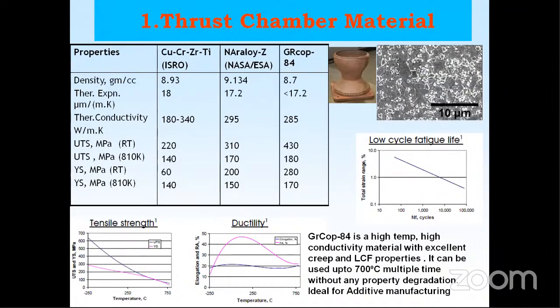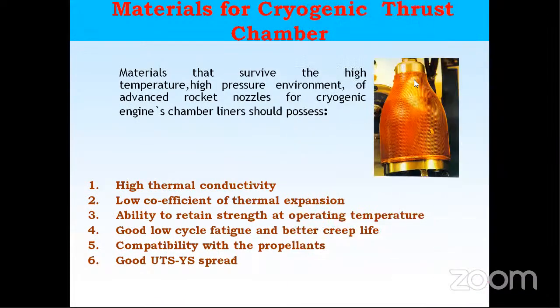Because what happens, my material, we make a chamber. This is a chamber actually. So we do brazing. We braze the foil and close the channels. The brazing temperature is nearly 1030 degrees centigrade, and after that it goes for engine operation. Actual engine operation is about 600 degrees centigrade. At that 600 degrees centigrade the precipitates come out and strengthen the material.